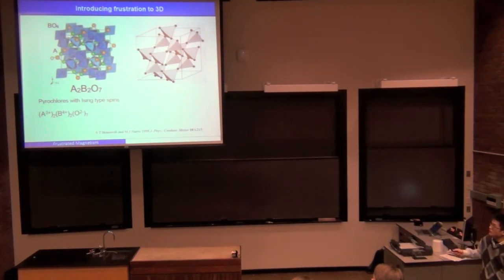And there is a group of materials that has this particular shape and chemical structure, called the pyrochlore. On the A site, there is usually a rare earth ion that carries a magnetic moment. On the B site, there is usually a transition metal. And this forms the structure here. Basically, the A sites and B sites are interpenetrating parallel lattices, which can be shown here. If we look at the A site only, it is formed by a structure of corner-sharing tetrahedra.